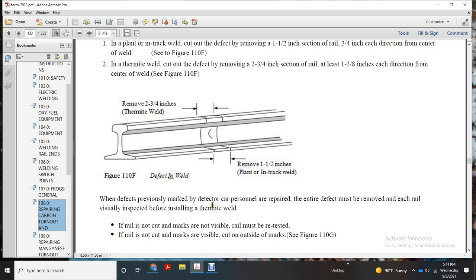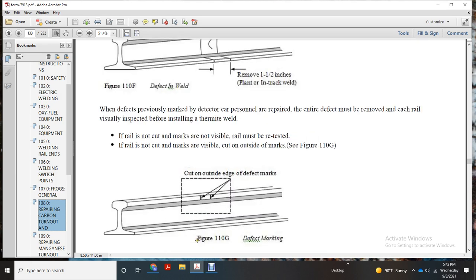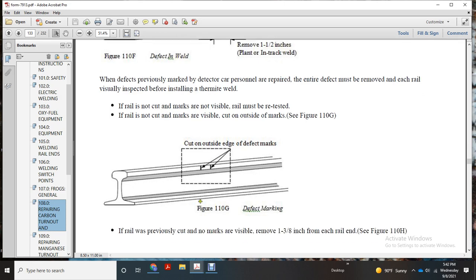When defects have been previously marked with the detector, personnel will repair them. The entire defect must be removed, with each rail end visually inspected before installing the thermite weld. If the rail is not cut and marks are not visible, the rail must be retested. If the rail is not cut and marks are visible, cut on the outside of the marks, on the outside edge of the defects.